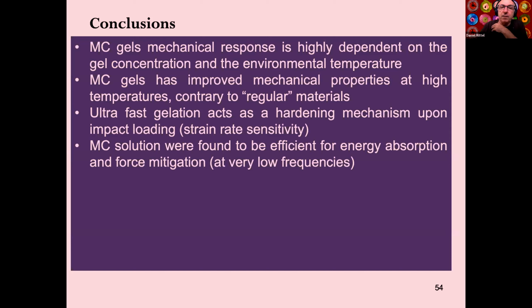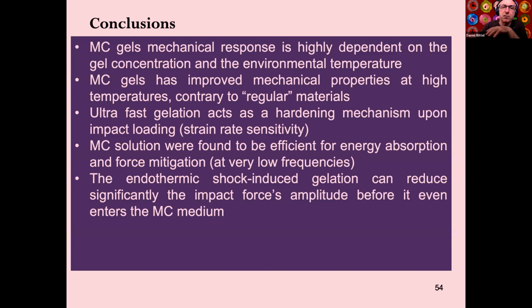Well, those materials have a significant capacity to absorb energy and to mitigate forces, even at low frequencies, structural ranges. And the endothermic shock-induced gelation can reduce significantly the impact forces. That's something that we measured as I was showing you.